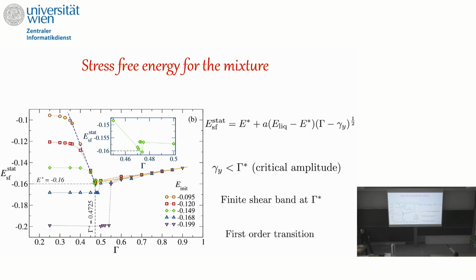Running out of time, you can say it later, but can you say something about the significance of that gamma y being less than gamma star? Yes, it means that the transition is at gamma star, okay? And gamma y, which was the one that I introduced at the beginning, the yield stress in the uniform case, is smaller. So it means that this form of the energy is valid starting from gamma star. When gamma equals gamma star, this is positive, so for gamma smaller than gamma star the energy is E star, and for gamma bigger than gamma star the energy is bigger, so you have a jump. This is the meaning, okay?